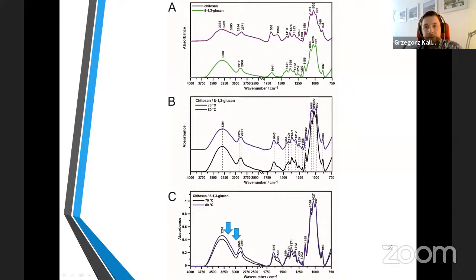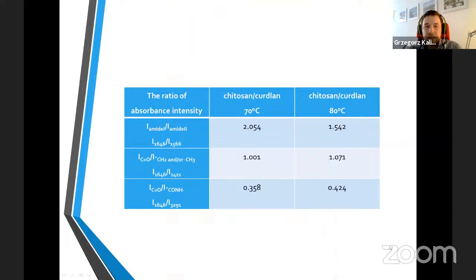They were found in chitosan, and it indicates interaction between an amine group of chitosan and presumably hydroxyl group of our glucan in our sample of 70 degrees. So more bonds were formed in lower temperature. This effect was also revealed by absorbance intensity ratio, for example, between amide 1 and amide 2, contributed to carbonyl and amine stretching vibrations of amide groups. So it also can be used to determine the changes in secondary structure of polymer chain.